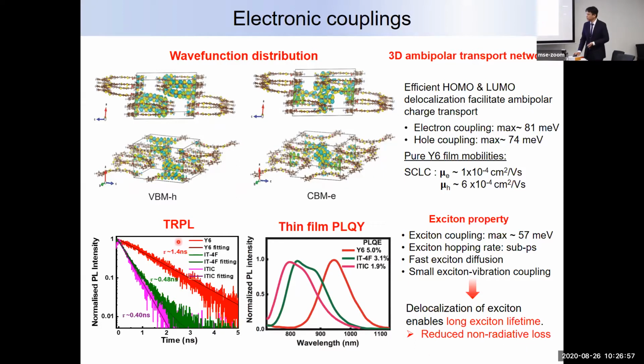So we can use time resolved PL, trying to measure the lifetime of this Y6 and also the previous IT4F linear non-fullerene acceptor. You can see the lifetime is 3 times higher than the IT4F, right? So the Y6 has a long lifetime, and the PL quantum yield is also very high, right? 5%. I think Professor Ji Yun recently published a Nature Photonics paper, exactly talking about breaking the energy gap law, right? It's a very small band gap material. You need to have these properties, okay? Decoupling of the vibronic and also the excitonic nature. And this material is also a very good infrared LED material, right?